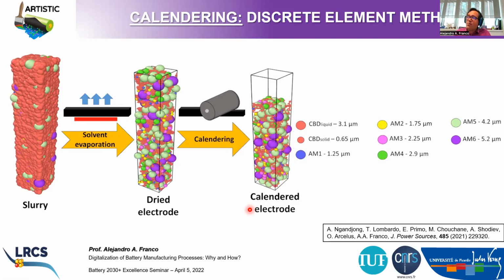In order to model the calendering process based on the physics-based approach, we use a technique called discrete element method. This technique is like molecular dynamics. So you describe here the interaction between particles, but in this case, instead of describing the interactions through Lennard-Jones or granular Hertzian potentials, you will describe interactions through mechanical forces, right? More or less. So here you have as an input of this discrete element method model the electrode microstructure predicted from the drying model, okay? And remember that the input of the drying model is the slurry microstructure predicted from the slurry model, right? So you see that the models are sequentially connected. So it's really a digital twin of the real manufacturing process from the slurry to the calendering, right?